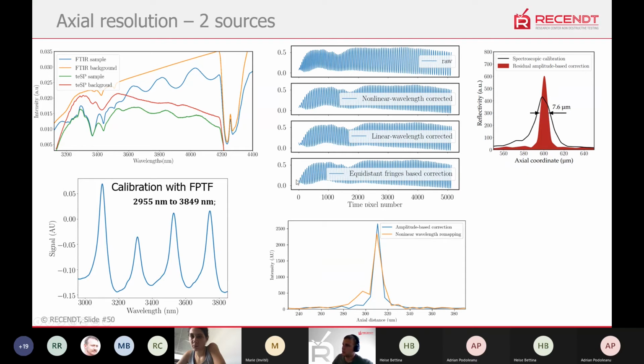Residual nonlinearities were corrected using amplitude-based correction. So it's more or less similar to the zero crossing method, where we track the position of the peaks, and we know that they should be equidistantly spaced, and we make them equidistant. The function that does this, the calibration vector, is just stored afterwards in the software. That's how it was done, and we could get quite good resolution for mid-infrared OCT because of the very broad range.